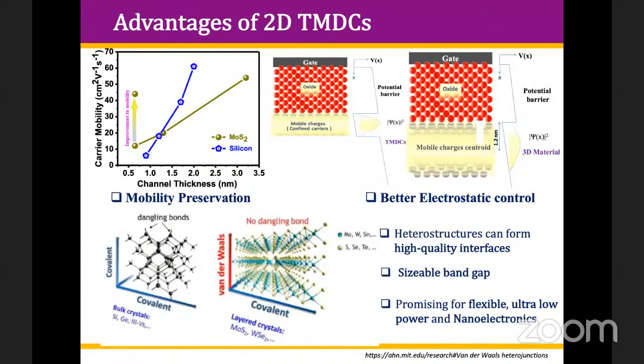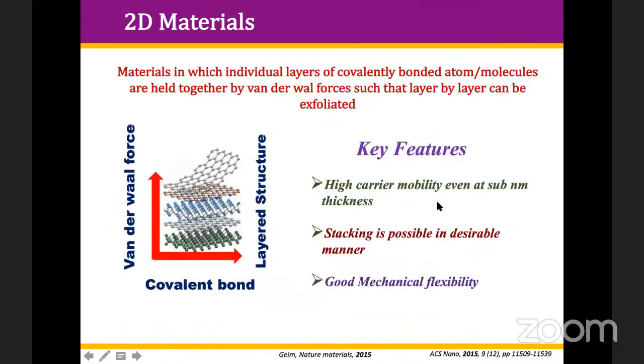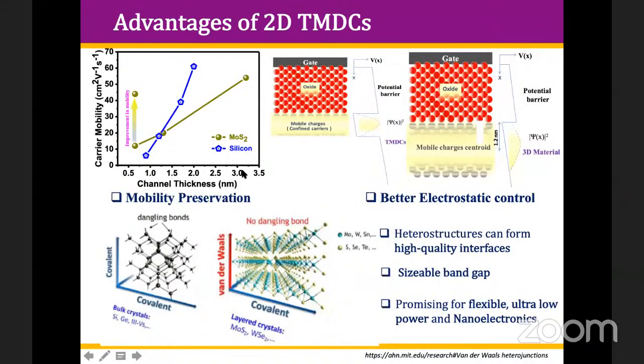What is the advantage of 2D transition metal semiconductors? You see here, as I mentioned about the carrier mobility, high carrier mobility even at sub nanometer thickness. If we reduce the thickness of the material, the blue is the conventional silicon material. If you reduce the thickness of silicon, the carrier mobility decreases significantly. If you go below 2 nanometers, you can see it almost comes to 0 or very small, around 5 or 3 centimeter square per volt per second. Whereas in the case of MoS2, even if your thickness is small, the carrier mobility even up to 0.5 nanometer is around 10 centimeter square per volt per second. So that's the advantage, that significant mobility is present even for smaller thickness of 2D materials.